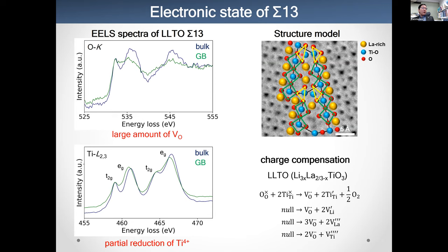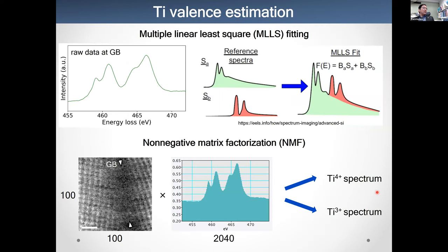So this is because of the formation of oxygen vacancy and titanium 3+. So we need to consider charge compensation, because a lot of oxygen vacancy is introduced. Maybe charge balance is needed, and there is a possibility of lanthanum vacancy, lithium vacancy, and titanium vacancy. I'm going to talk about this later.